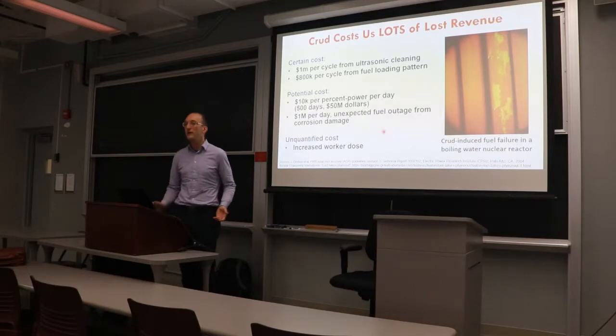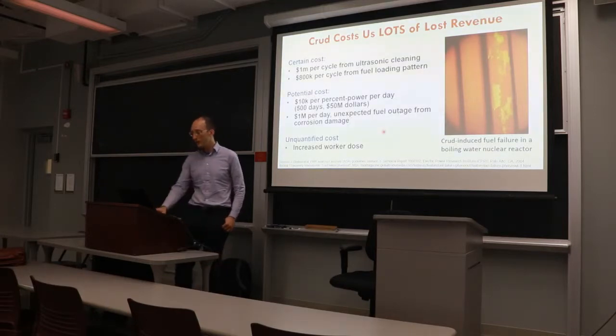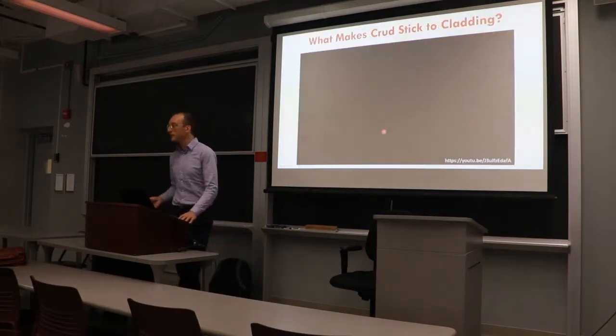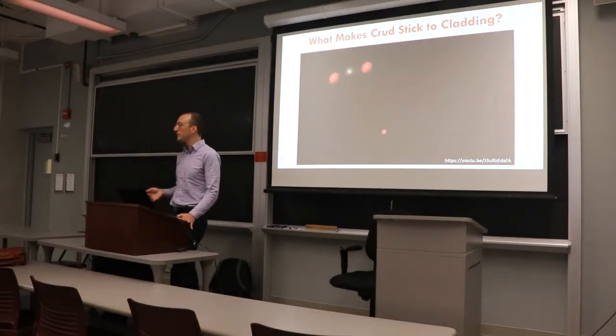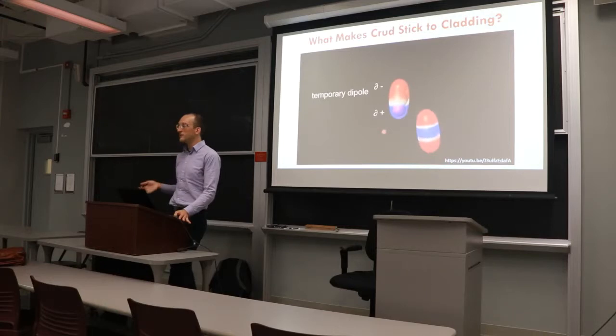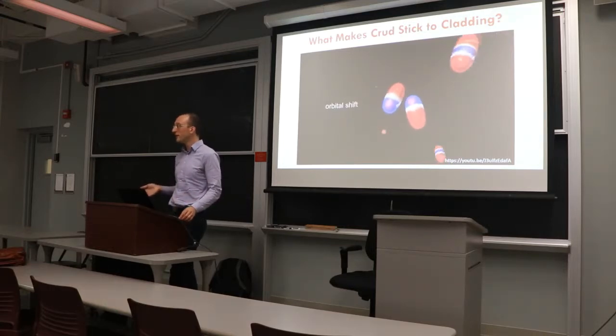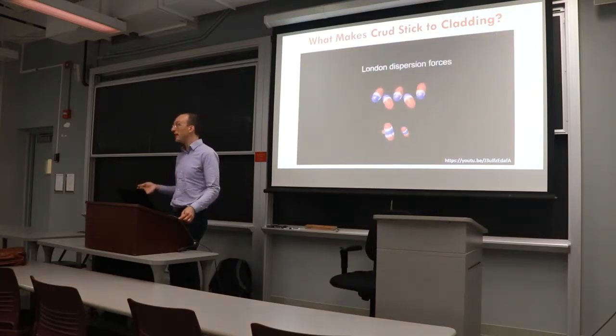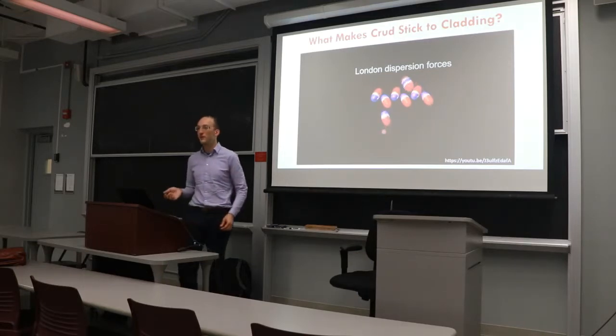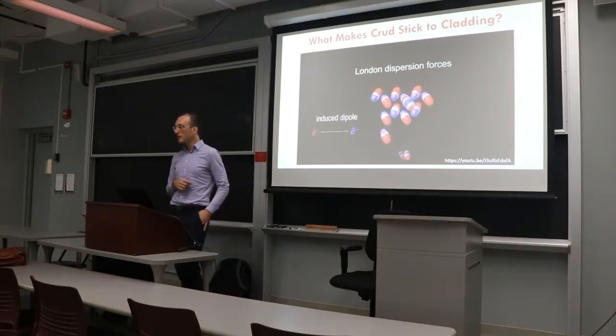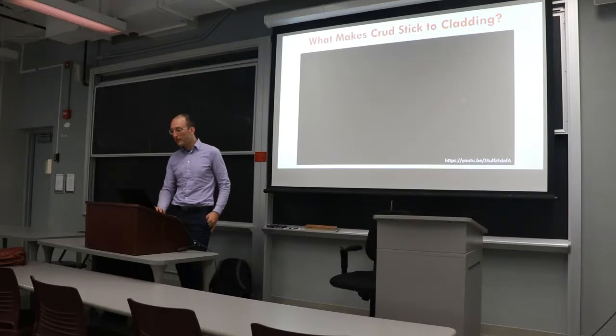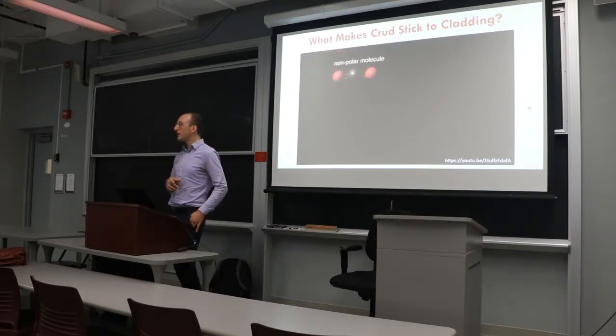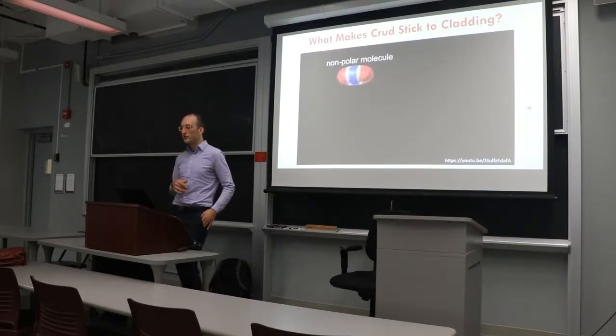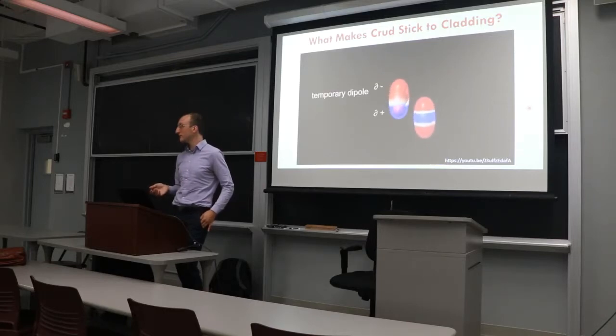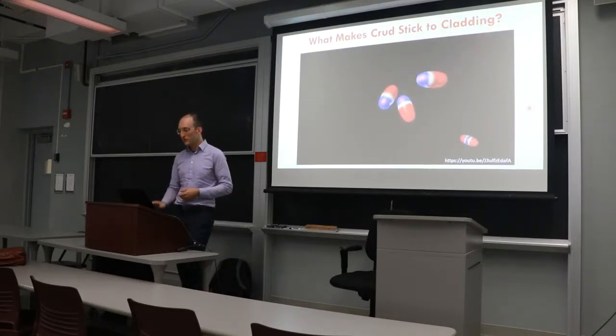And so we thought, what actually makes crud stick to fuel cladding? We looked at all the possible surface forces, and we figured it came down to induced dipole interactions, or van der Waals forces. There's no magnetism going on here; Zircaloy is not magnetic. There's no hydrogen bonding. There's no biofouling, because nothing survives in the primary loop. And due to some measurements that we made a little earlier, we know that the static dipole component of surface forces drops off at around 200 Celsius. That leaves van der Waals forces.